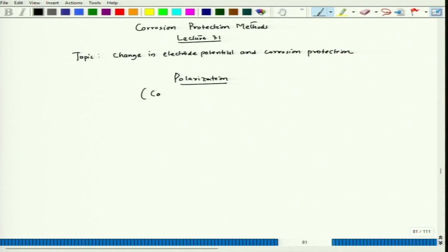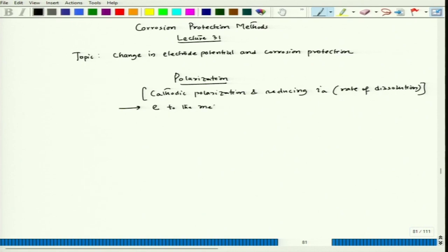and we are specially talking about cathodic polarization and reducing IA, or rate of dissolution. Okay. So, that is possible if we send electron to the metal. And this actually enhances the rate of cathodic reaction. Enhances, and that actually reduces IA. So, this was done like this, if we recall.